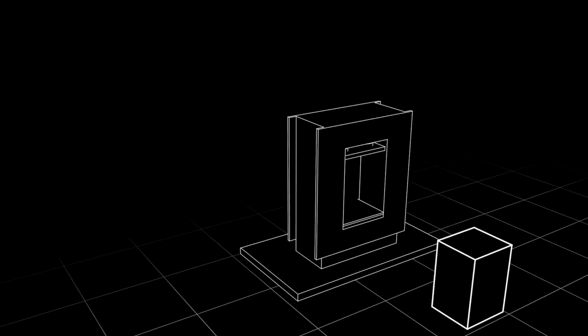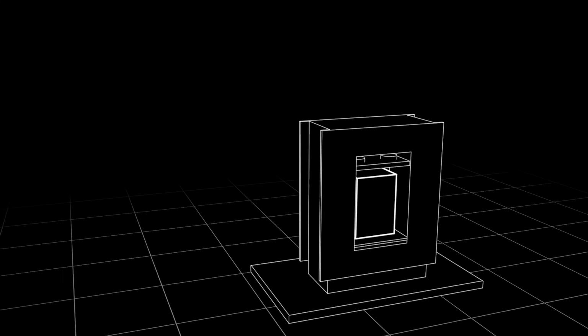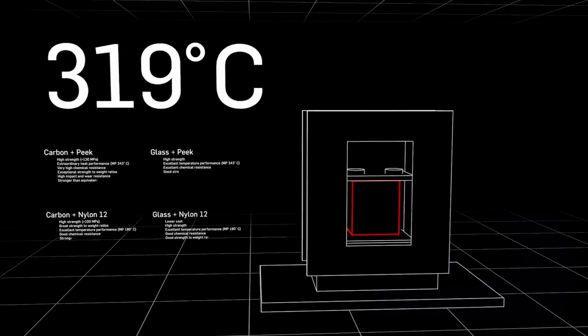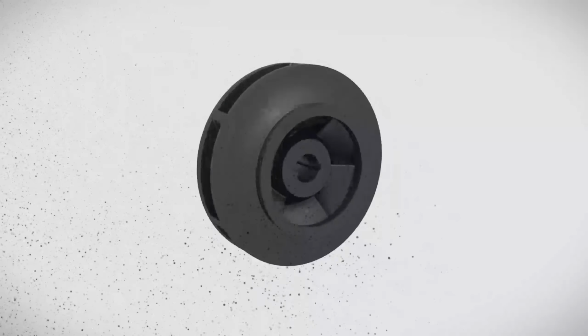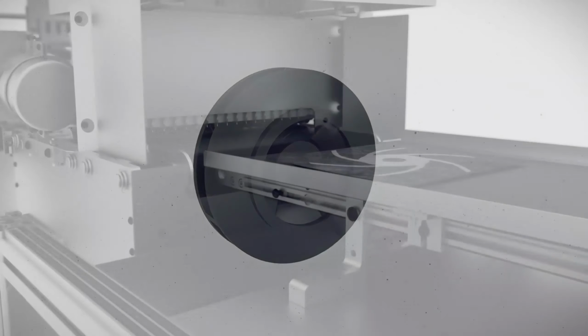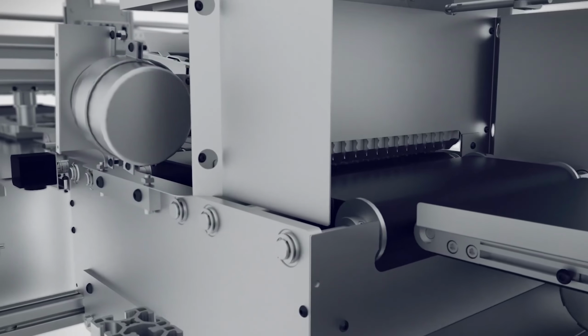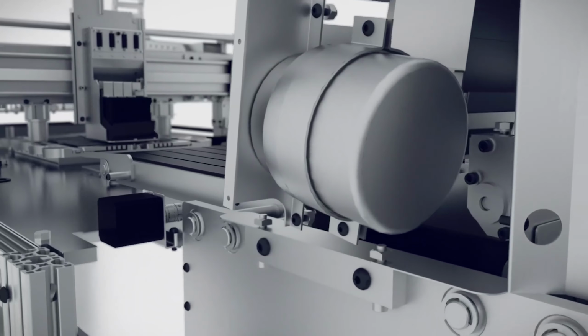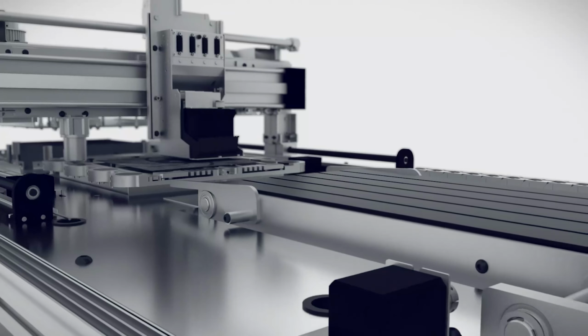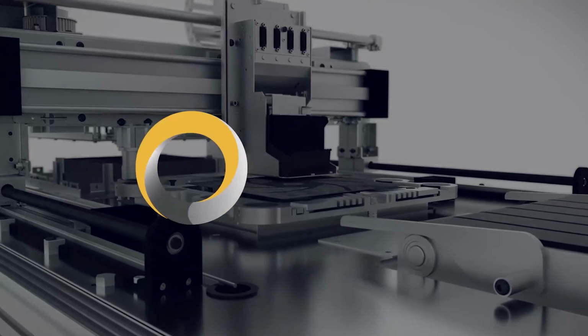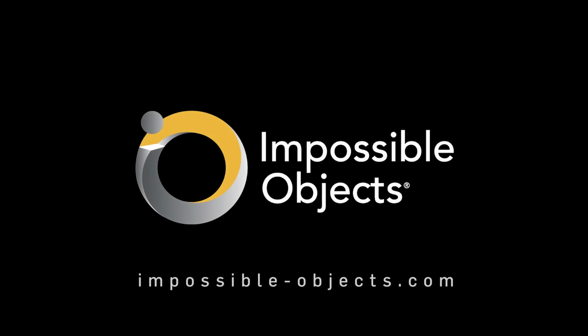The final stack is compressed and heated to the melting point of the polymer. The particles melt and encase the fibers to fuse the layers together into a solid part. The fused build block moves into the sandblasting unit. The uncoated fibers are removed, revealing the finished part. Impossible Objects' CBAM printing process produces stronger parts faster than traditional 3D printing methods with a broader range of material options. For more information, please contact Impossible Objects today.